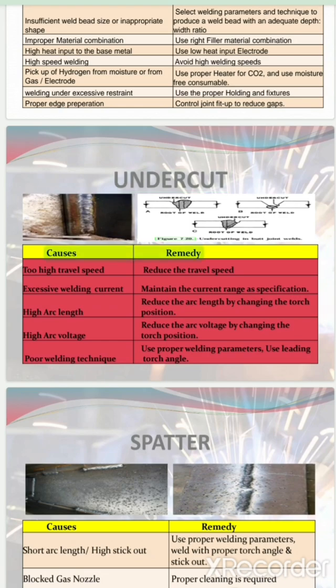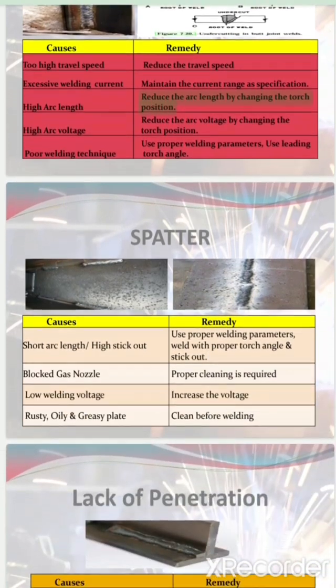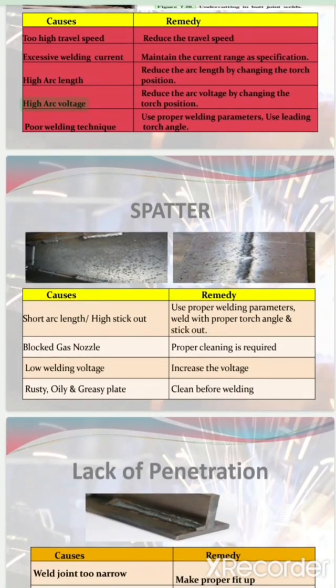Undercut. Causes and remedy: too high travel speed, reduce the travel speed. Excessive welding current, maintain the current range as per specification. High arc length, reduce the arc length by changing the torch position. High arc voltage, reduce the arc voltage by changing the torch position. Poor welding technique, use proper welding parameters, use leading torch angle.